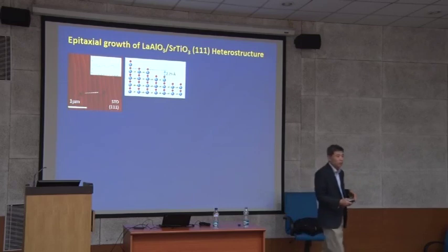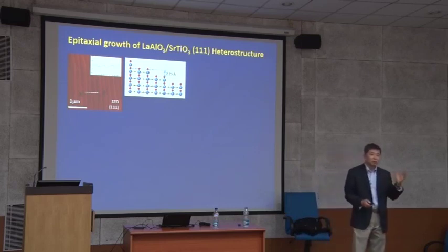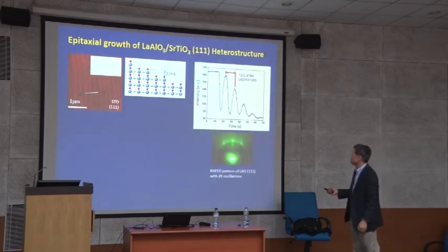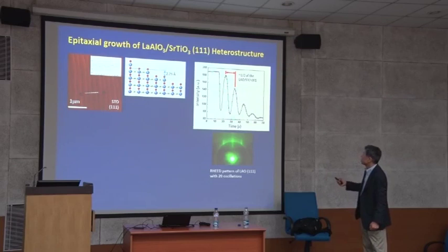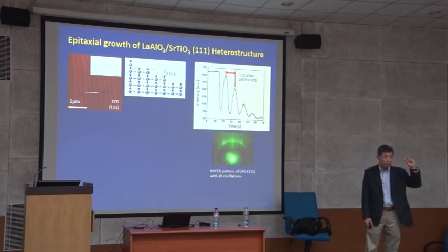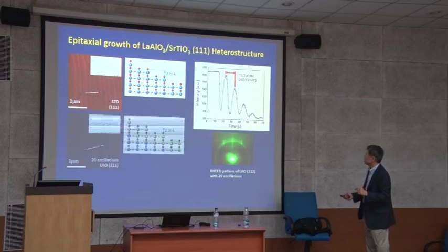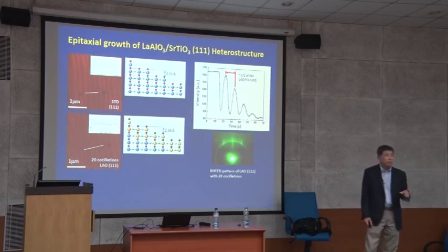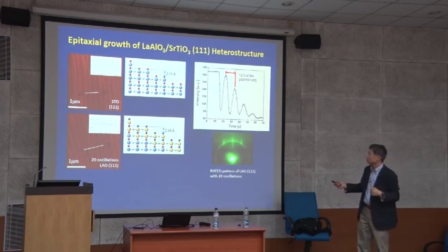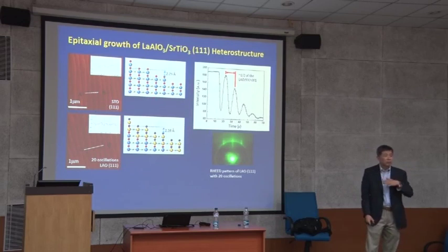What we found is that in the temperature range around 500 to 550 degrees C, you get very nice epitaxy. It grows very smooth and doesn't form the amorphous layer. You can actually see very nice oscillations. Each single oscillation corresponds to one bilayer. Remember the bilayer? And in the lanthanum aluminate you can see a beautiful step structure. It does not form facets. It grows atomically flat interfaces, so we have these kinds of interfaces from here to here. That means you can make a very nice interface.